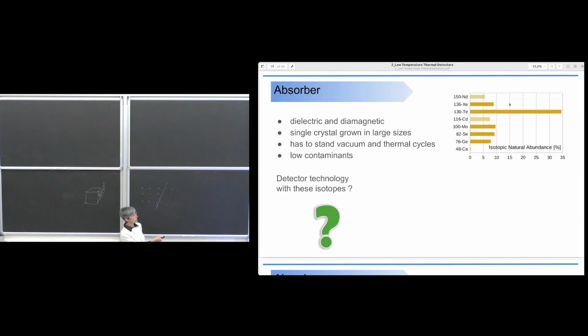So for this isotope, you can rely on bolometers. Selenium, do you know any detector made of selenium? Selenium is a very good scintillator, with a very high light yield, even at room temperature. The main problem is that it's very difficult to grow crystals, especially single crystals. Therefore, it was used a lot, and still it is used, I think, for alpha detection with very small scintillators. But as a scintillator detector for particle physics, I think it was never used.